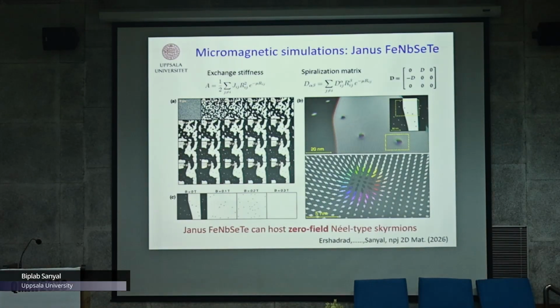And one of the variants is the Janus structure. Then you have selenium and tellurium on opposite sides that break the inversion symmetry, and you can expect to see something like skyrmions here. And definitely we see the presence of Néel skyrmions, which also happens at zero applied magnetic field. So which can also be interesting for some experimentalists.